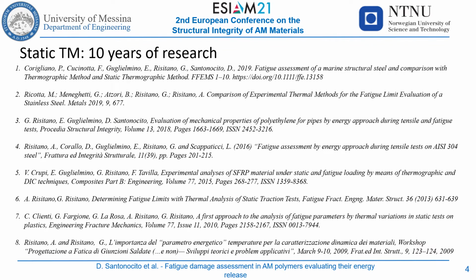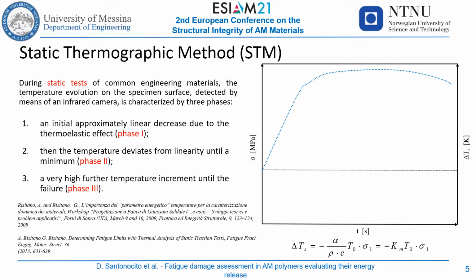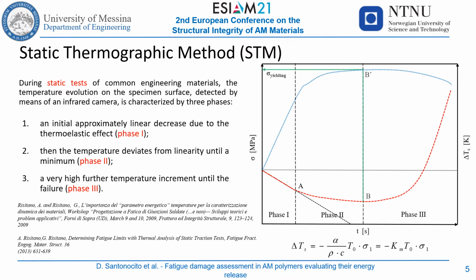The static thermographic method has been developed during the last 10 years. The first paper by Risitano and Risitano was presented in 2009. In 2013, Risitano and Risitano proposed the static thermographic method as a rapid procedure to derive the fatigue limit from a tensile test. During static tests of common engineering materials, the specimen's temperature is characterized by three phases. An initial approximately linear decrease due to the thermoelastic effect following Lord Kelvin's law. Then, in the second phase, the temperature deviates from linearity until a minimum, and finally it experiences a very high further increment until the failure.